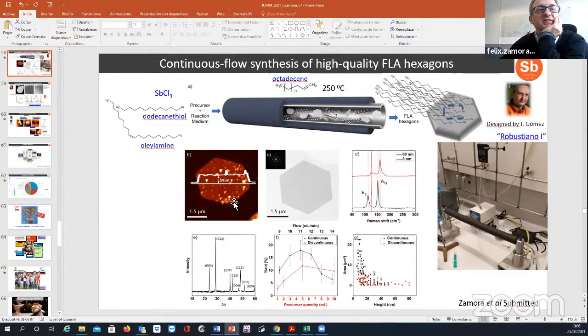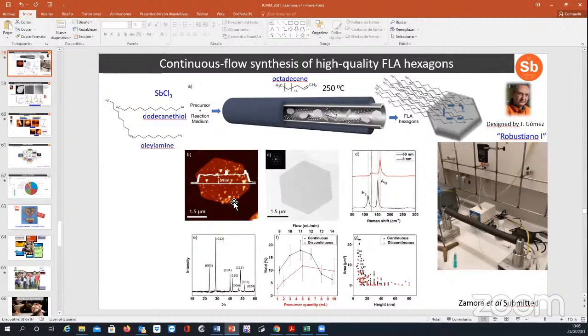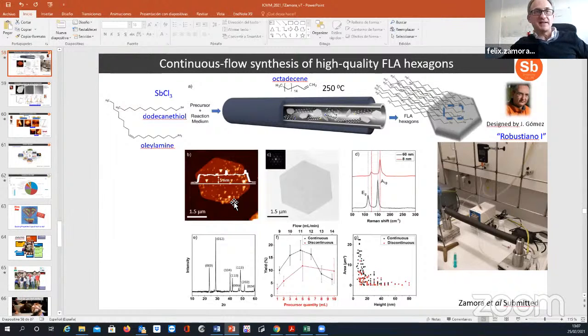You mean this sample? Yeah. As far as we are trying to produce this material in large quantities, what we observe is that it's not trivial to adjust the experimental conditions to decrease the thickness. So probably 5 nanometers is the smallest. Maybe we found something like 3 nanometers sometimes, but not statistically, though you can find them eventually. In a sample, you can find some small flakes, but just few of them.